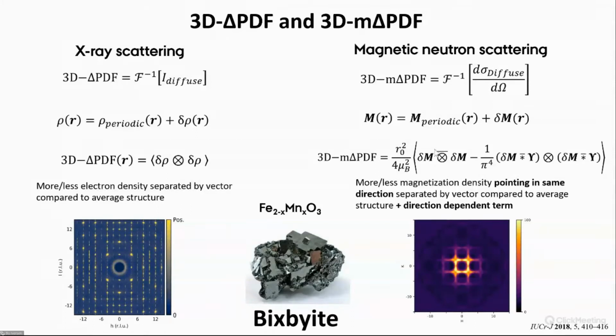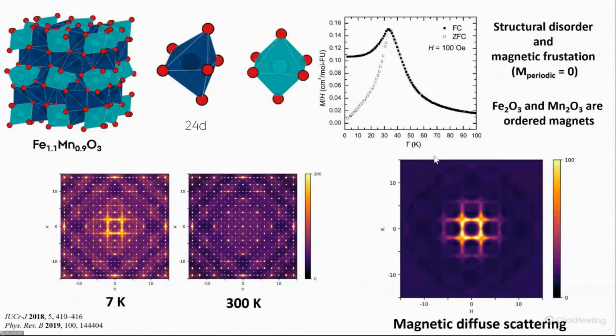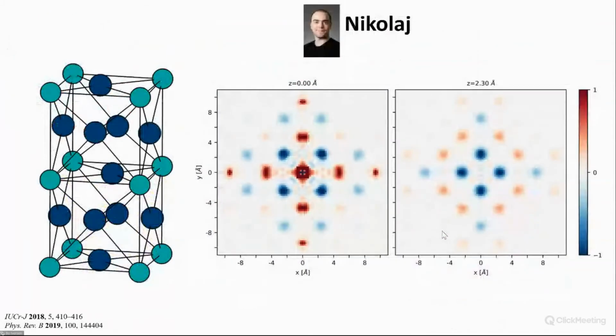antiferromagnetic or ferromagnetic correlations. And one example is bixbyite. This is a natural sample from Utah where you have a disorder on the iron end. So it's Fe2O3 as the base formula, but this is a mixture with iron and manganese. You have two metal sites, one quite octahedral, one very distorted. And the trick we used here was that we measured the neutron data at room temperature and then cooled it down to get the magnetic diffuse scattering. But then you can subtract the structural disorder from this map, and then you end up with just the magnetic diffuse scattering in the system. And this you can Fourier transform, and what you then see are the magnetic correlations.